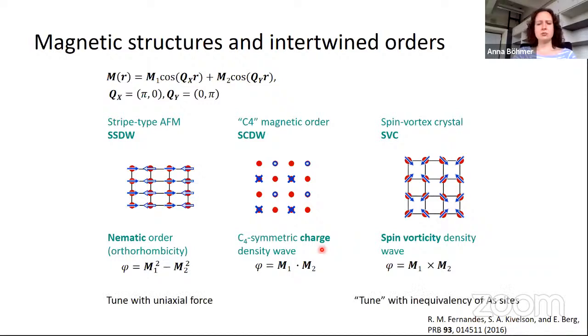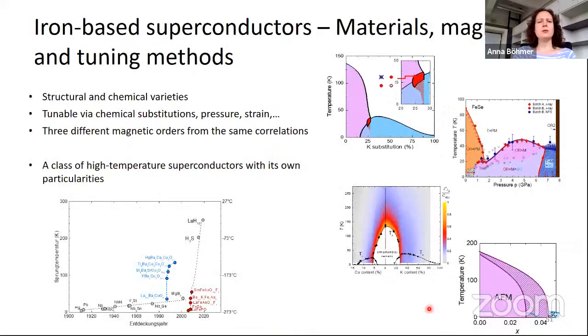And this led us to some tuning using some forces, coupling to this, or tuning using the structure, this alternating layers. Here we couldn't find out how to tune this. So finally, on materials, magnetism, and tuning methods in iron-based superconductors, we've seen a lot of structural and chemical varieties of the materials that are tunable, that properties can be changed using chemical substitutions, using pressure, using distortions, using the c/a ratio, as we did with the substrate.